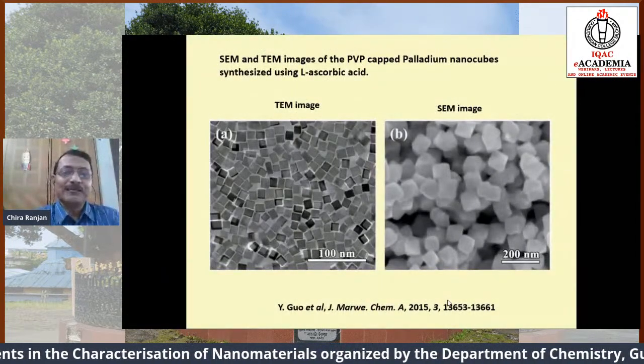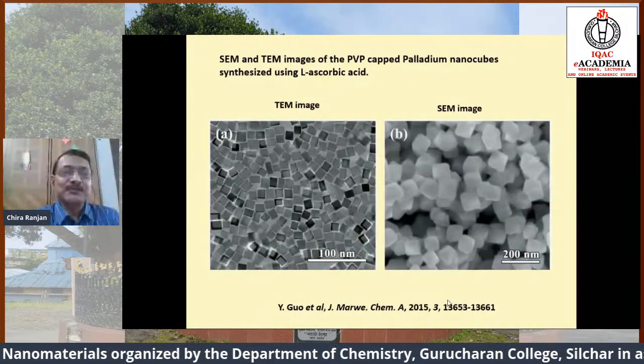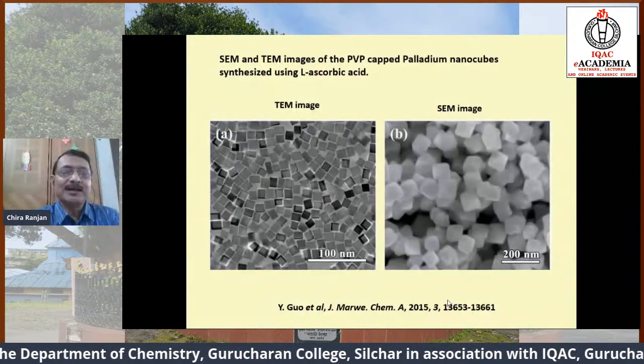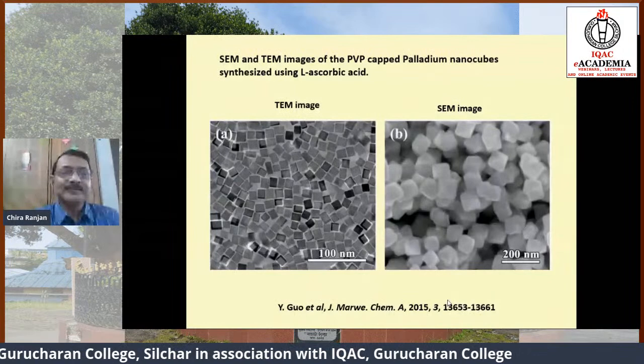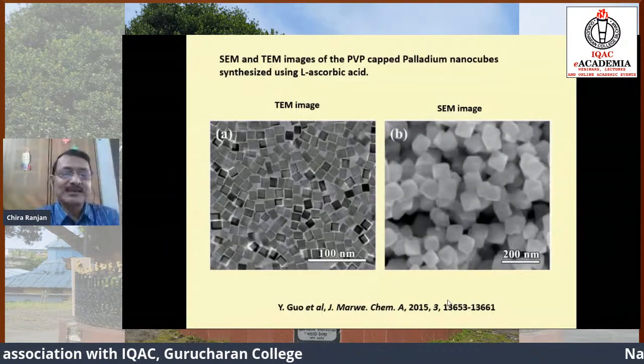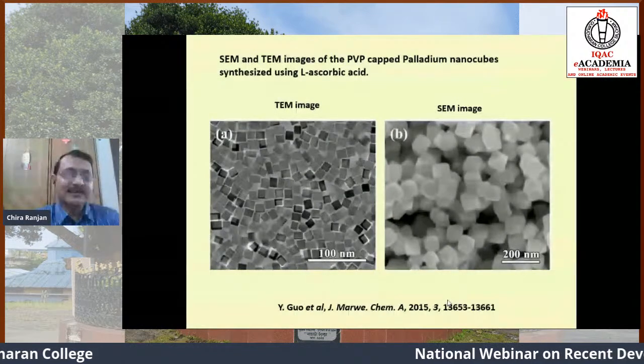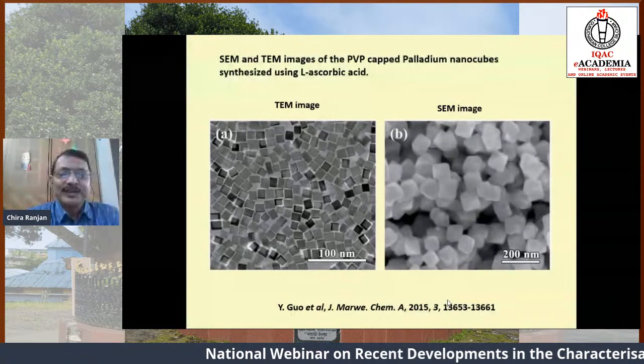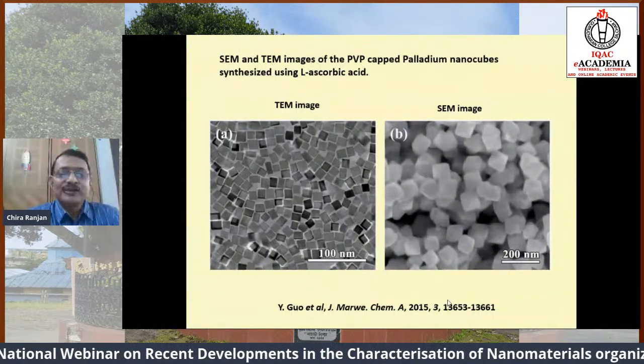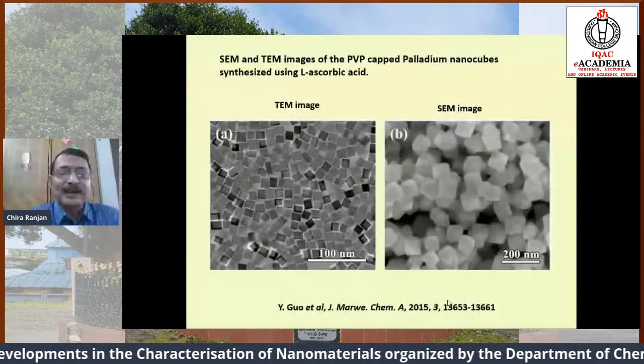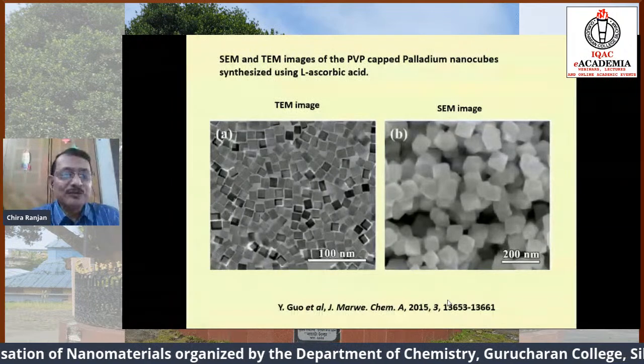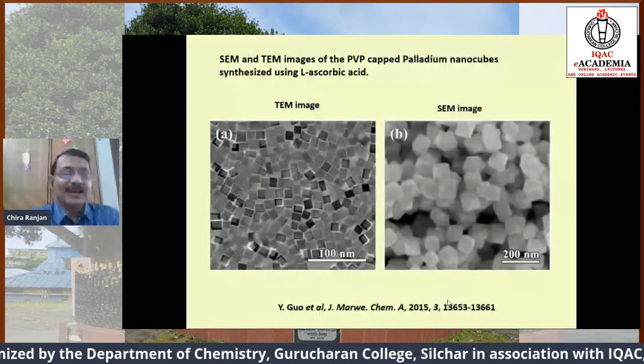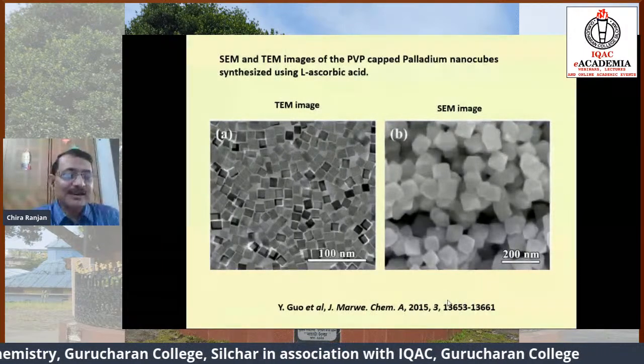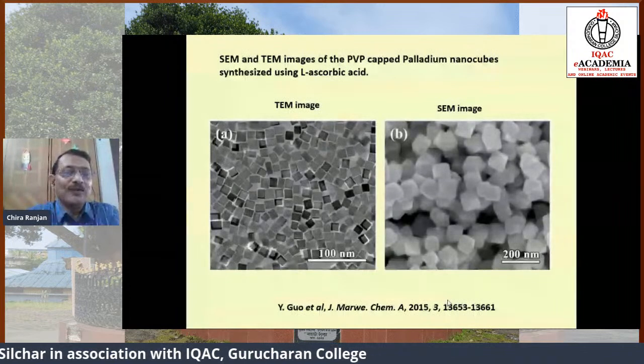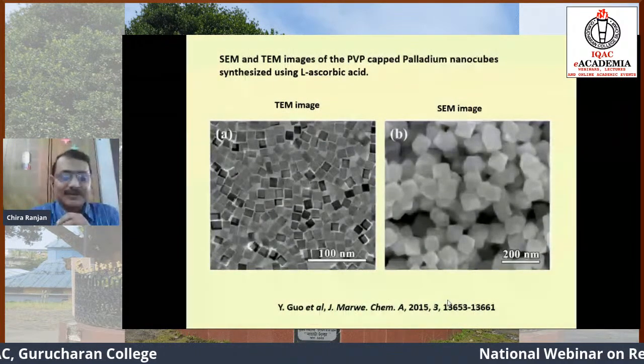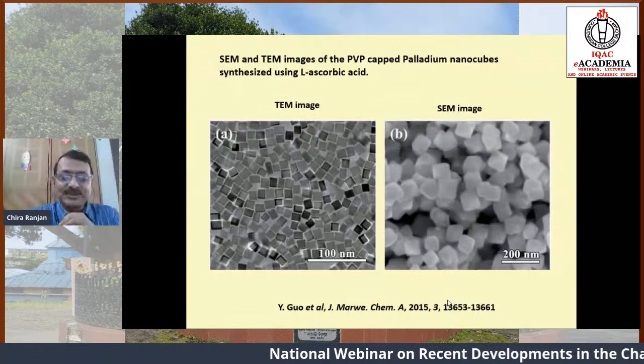This is also palladium, but this time you have a nanocube type of structure, and the particles were synthesized using ascorbic acid. You can see beautiful SEM images. It gives a kind of mosaic texture, and the TEM image and also the SEM image clearly tell the cubic type structures. So the shapes and the nature of the clearly separated particles are known from both the TEM and SEM images. This work was published in 2015.